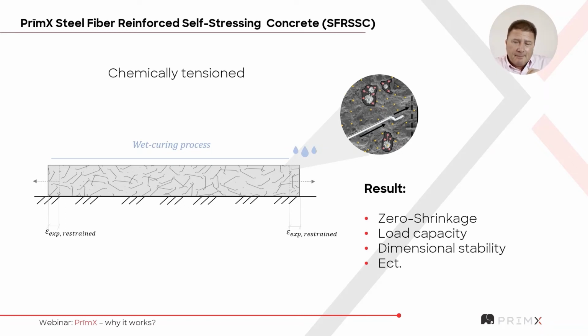Interestingly, as the mortar starts to expand, because the ettringite is pushing it apart, it actually puts the steel fibre into tension, stretches it, and locks. And that places the concrete in a state of permanent compression. So our reinforcement, which is evenly distributed throughout the concrete, throughout the mortar matrix, from left to right, near to far, top to bottom, doesn't matter where you look at it, you'll find the same amount of reinforcement, and you'll find the same process going on, which is the reinforcement being stretched, locked, and the concrete placed in permanent compression.